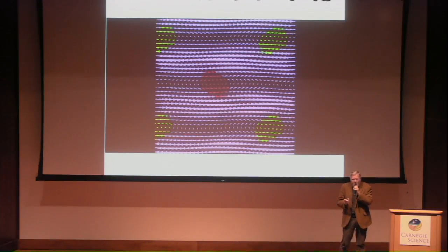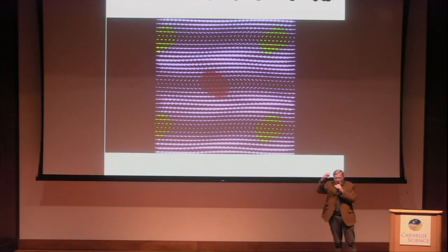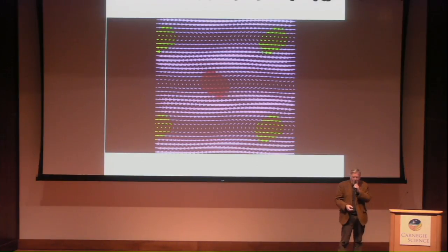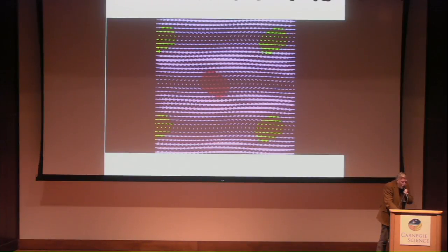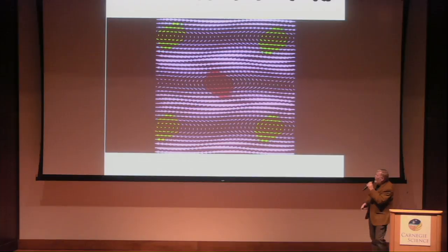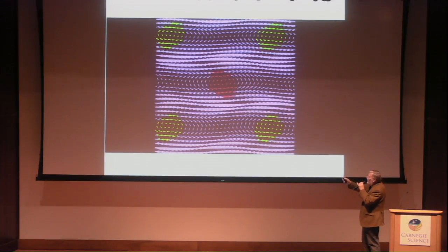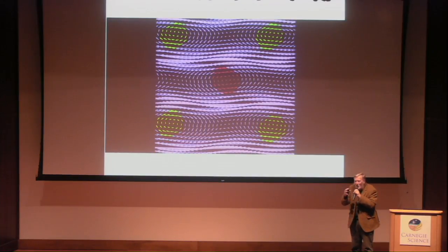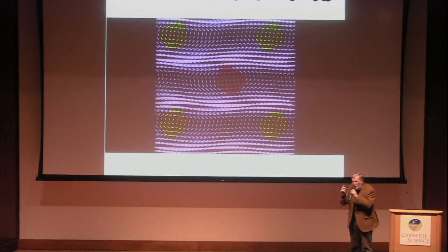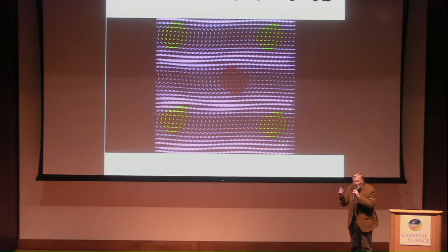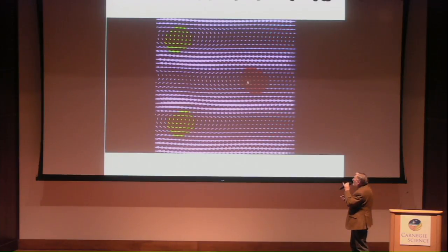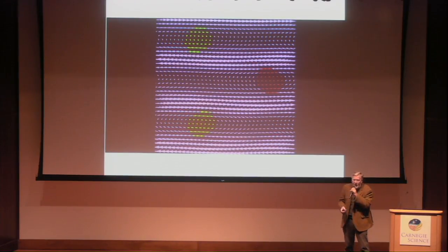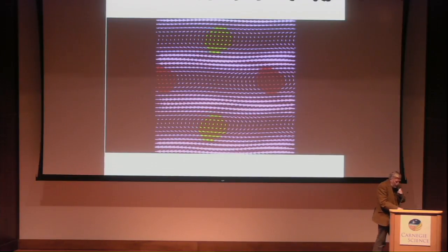So these twin boundaries are in fact always, if they're close enough to each other, always connected by vortices. And these vortices themselves are, of course, an excitation. So you can see here, we don't put any forces on, we just let temperature do its work. And you can see the vortices are actually slightly fluctuating. So they're not stable. It's not like the twin boundary. The twin boundary is totally stable. It wouldn't move a bit by temperature. But the vortices here are really on such a low energy scale that even temperature can move them around.